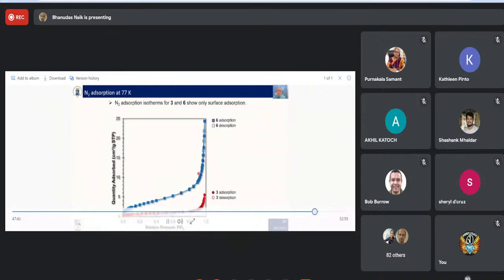And you can see that the nitrogen isotherms basically show almost no adsorption. So 3, for example, these have to be the anhydrous compounds. 3 and 6 are basically the same as surface adsorption. You have no porosity whatsoever in these compounds.